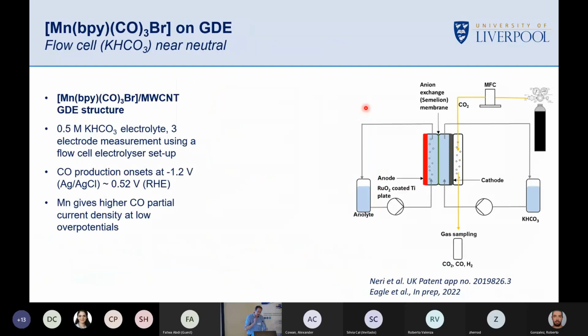So can we put it on a gas diffusion electrode? And Marc Robert's group has shown that we can do this with molecular electrocatalysts, and really led the way putting some cobalt and iron catalysts onto the surface. So there have been a few studies now with molecular electrocatalysts on gas diffusion electrodes running at high current densities. So could we do it with manganese? So we just now take our carbon support, a porous commercial gas diffusion electrode from the fuel cell community.